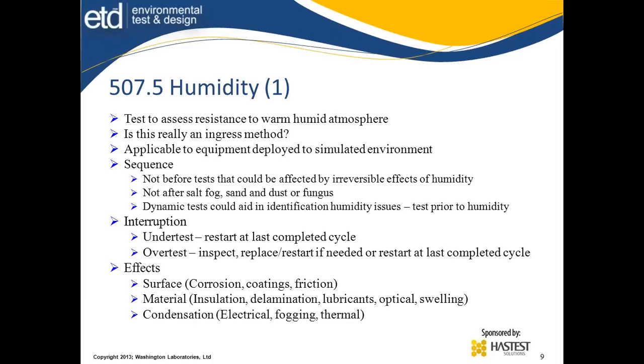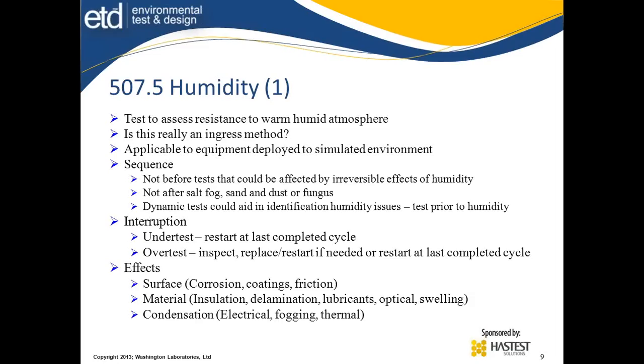The sequence calls for not before tests that could be affected by irreversible effects of the humidity. So therefore, if I have the humidity causing an issue, a corrosive effect that I can't determine if salt caused it later or some other test caused it, I need to be able to separate the two. So you have to watch for these kinds of tests so that you don't mislead yourself into the effects when you get your inspection. Never after salt fog, sand and dust, or fungus testing. Those have effects on humidity and the ability to creep into systems. Dynamic testing could aid in identifying humidity issues prior to humidity. So sometimes doing dynamic testing prior to this could help you identify the issues. So in the sequence, you might put dynamic testing ahead of humidity.